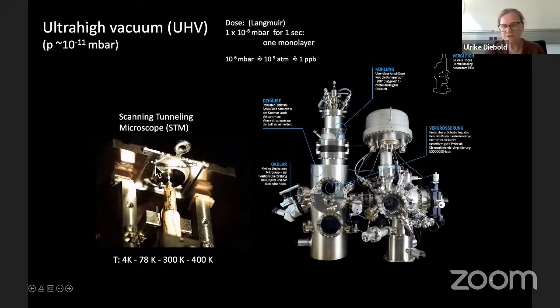Typically, we like to do microscopy with atomic resolution in combination with all sorts of surface spectroscopies, because that gives us this atomic scale insight. The best images we get are really at 4 Kelvin, so it's not only the atmosphere, it's also the temperature, and we also like to use single crystals. Whatever I say here is very idealized, but what we hope is to get some fundamental insights that people can then use in their thinking about more realistic chemical processes.